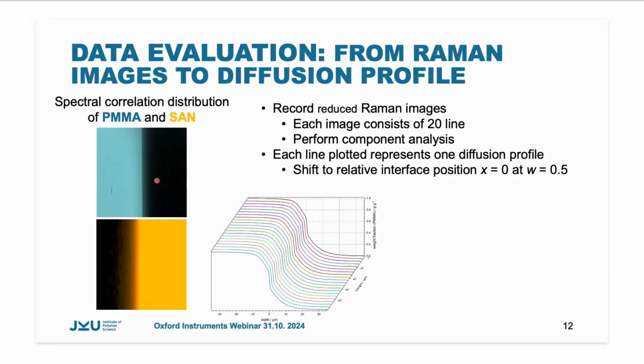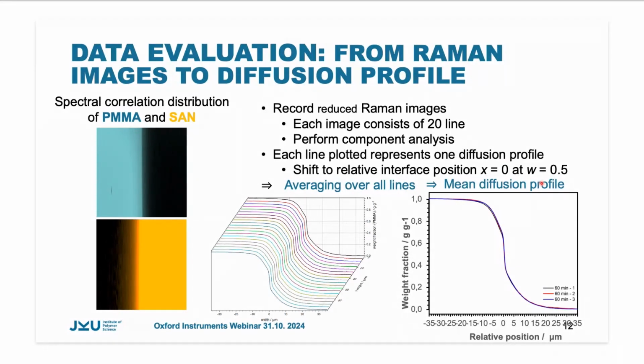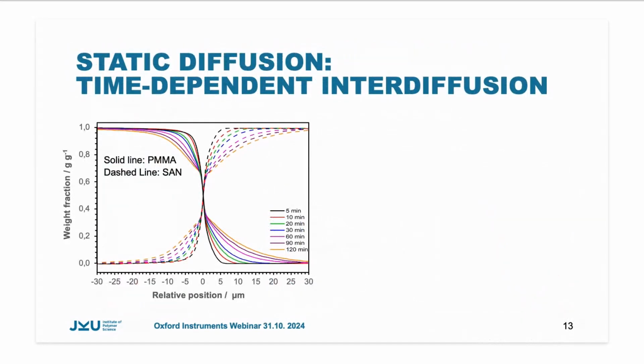These images show one thing, that we have here an interdiffusion area which does not really fit to each other. Therefore, we plot all the lines and we shift every line we recorded to a relative interface position, which is our reference position 0 and has a weight percentage of 50% of PMMA. Then we average over all the lines and then we get one mean profile which we can use for further analysis.